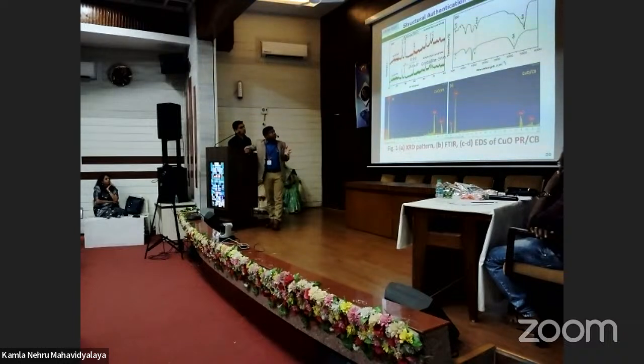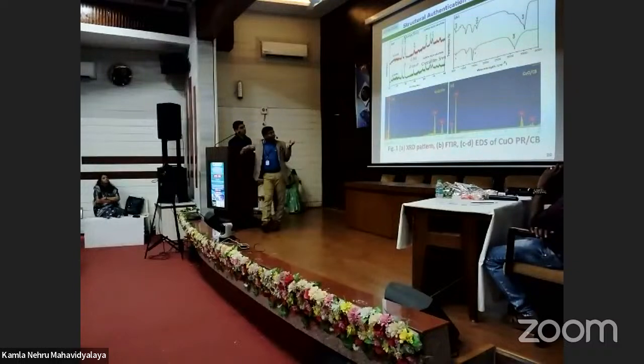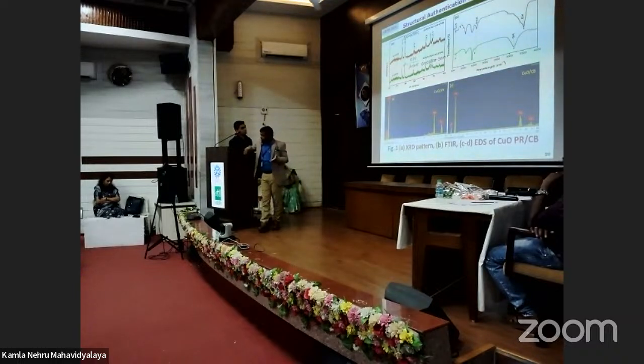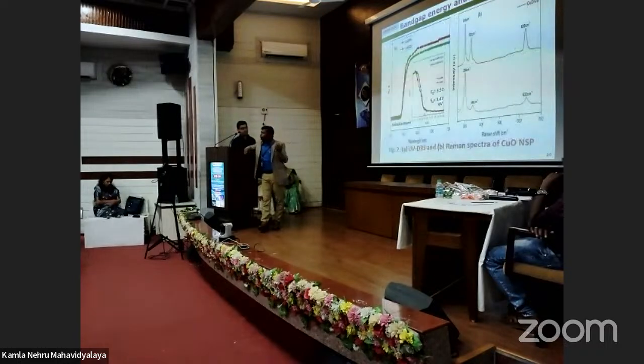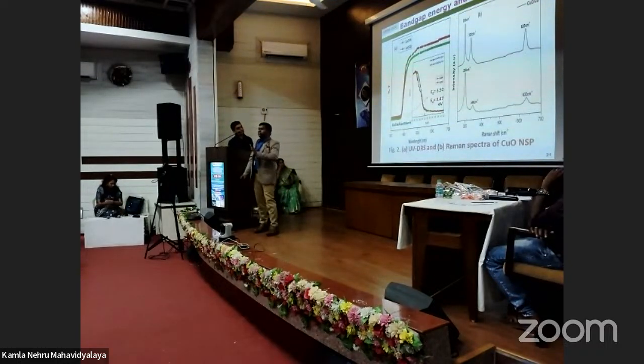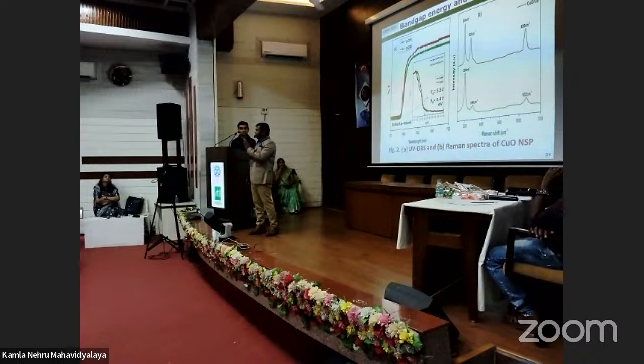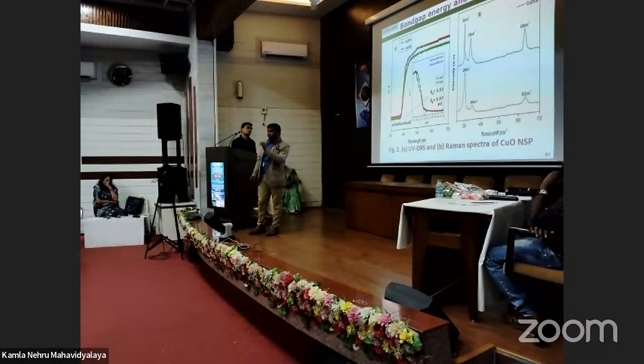And so after monoclinic, then it was Raman spectroscopy, then FTIR, then EDS. After EDS, we did carry out the XPS. XPS is most important next to EDS. After EDS, you do XPS to find out the chemical composition and chemical state, +1, +2. So it will give the exact oxidation state.